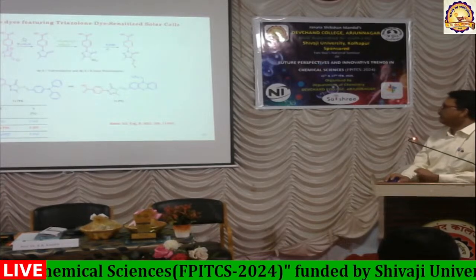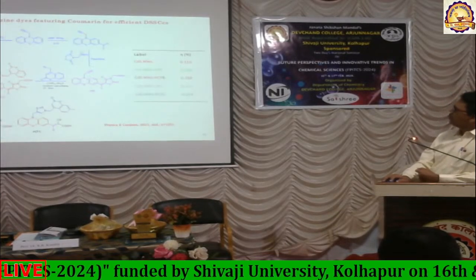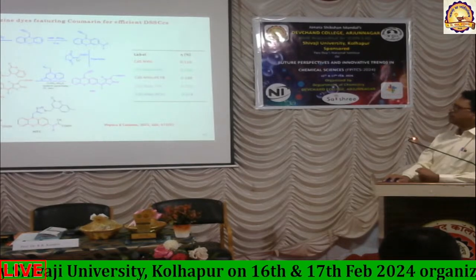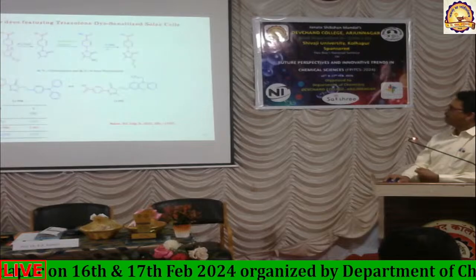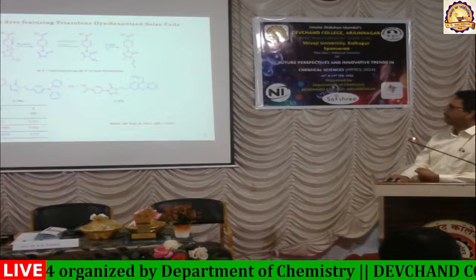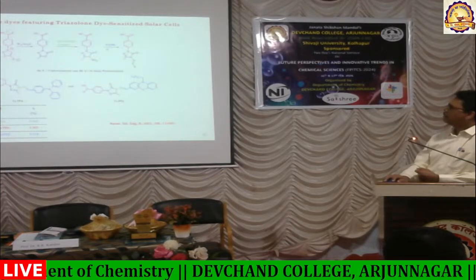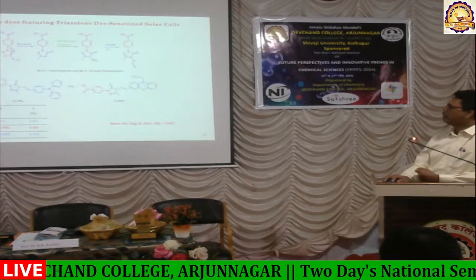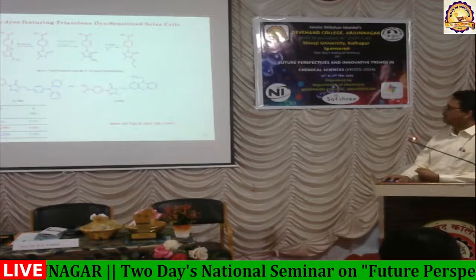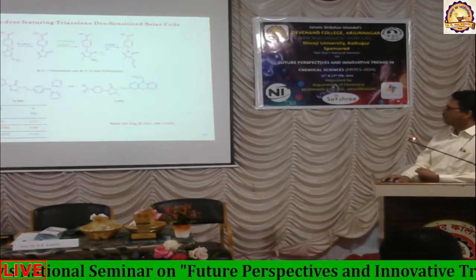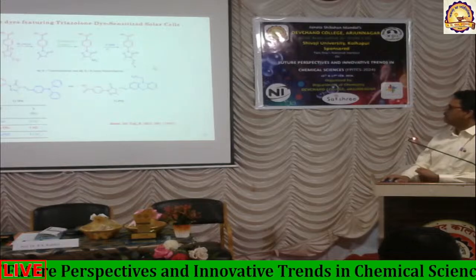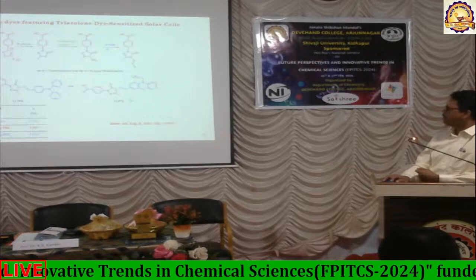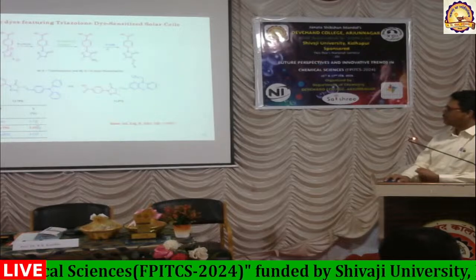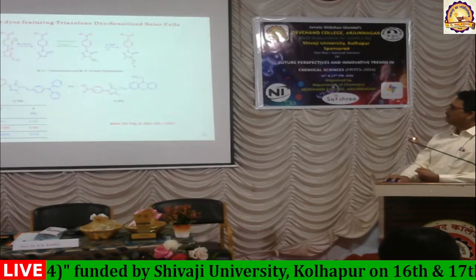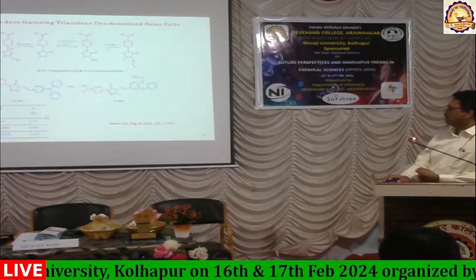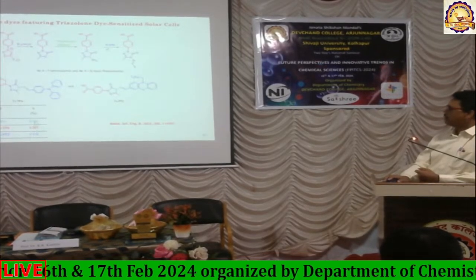So these are the phenothiazines. In the earlier cases we had to introduce a linker group purposefully so that it would link on the semiconductor. But here we took advantage of preparing our sydnone derivative, which was previously introduced with a COOH. We converted it into a triazole through oxidation, and then on the NH2 functionality we converted it to a simple Schiff base using such moieties. We checked their efficiency, and it was almost 3 times higher, and the intrinsic property of this COOH was checked here too.